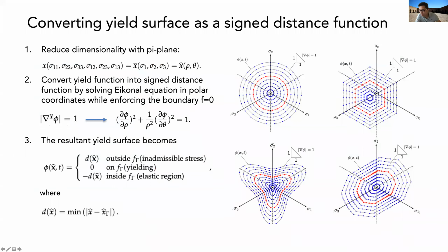So remember that in the original testing data, we would load the experiment or load the DNS until we observe the initial yielding point. And then I would draw a circle on that yielding point, right? But then I actually don't know anything inside and outside if I just link those points together with implicit functions. Hence I cannot compute the stress gradient, which is required to compute the plastic model. So what we came up with is that since we know the interior has to be the elastic domain, the exterior has to be the impossible domain, and the path of plasticity lies on the yield surface, we can convert any arbitrary yield function into a signed distance function.